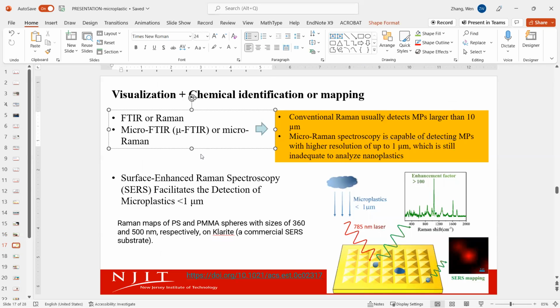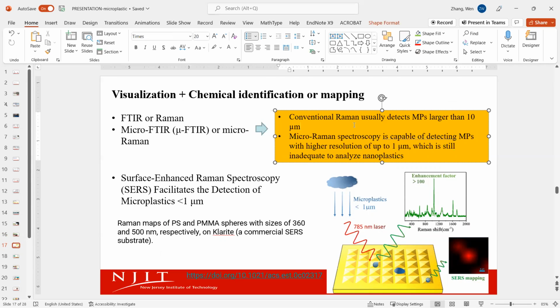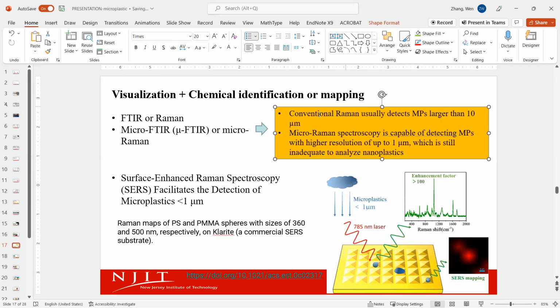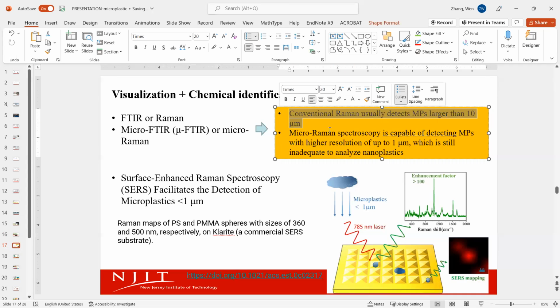So here I want to highlight a few common techniques that people have been using, like FTIR and Raman. And you may wonder, since they are very famous and also very powerful, why can't we just use them? The problem is this: Raman and FTIR have a very limited spatial resolution. Spatial means how small you can see. For a good Raman spectrometry, you may be able to detect plastic particles down to around 10 micrometers.